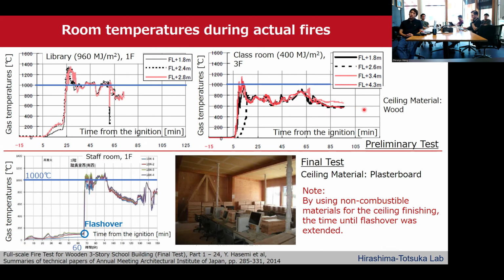In the preliminary test, the ceiling material was wood. And this is the other test. In the final test, the ceiling material was changed to plasterboard, and the fire load materials on the floor were also changed. This change considerably extended the time to flashover. However, the temperature during the fire decay phase remains high for a long time.